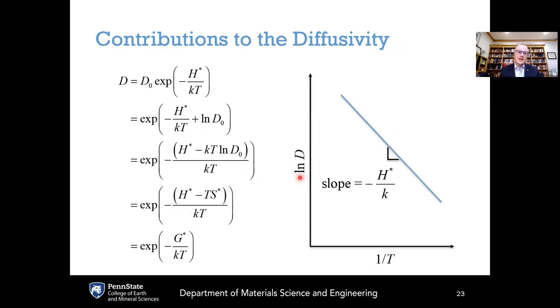Now, how do we get this? If you've got the natural log of the diffusion coefficient on the y-axis versus 1 over temperature on the x-axis, you can measure the slope of that Arrhenius line here. And that slope is equal to minus the activation barrier for diffusion divided by Boltzmann's constant. So take the slope, multiply it by minus Boltzmann's constant, and that gives you the activation enthalpy for that process. And playing around with this formulation, you can describe the same curve in a few different ways. The usual way is the diffusion coefficient is equal to D0 times the exponential of minus H star over kT.